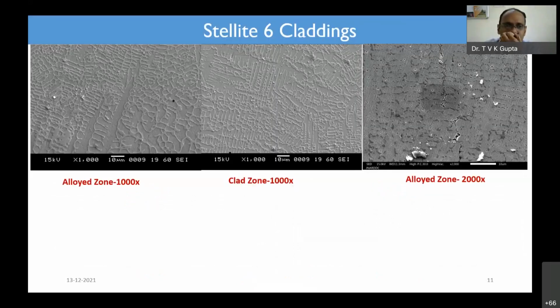Now, for the Stellite 6 cladding, they were not using high powers, because they are more worried about their system. They want a high deposition rate and faster movement also. Because every industry partner says that the faster the work is done, the better for them. So what they used to do is complete the process at a very fast rate and high deposition rate. But that will not work. If you use a high deposition rate and high scan speed, you do not have enough time to fuse the material, and you will see a lot of wastage where there is no deposition. So we asked them to change that, and we did a pure scientific analysis. To convince them, we took almost 6 months, but finally they got convinced, and they have helped us a lot. Actually, we should thank Srinath Engineering Industries.